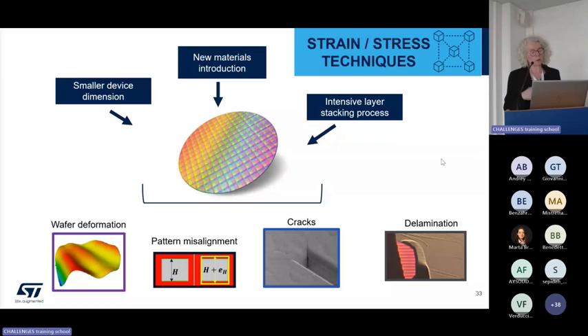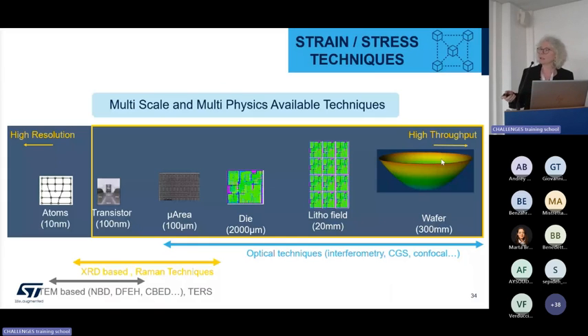So we've seen a growing focus on this demand for stress and strain measurement. What we have in hand in line is what is here in blue. We rely so far a lot on optical techniques. At the wafer level, we measure the deformation we call bow or warp. We can also use interferometry to get information at the litho level, the die level. But for a smaller area, not really the transistor but something like 100 micron square, we have to move at least to Raman or XRD. If we go even further, to the transistor itself, then we need to move to characterization techniques like TEM lamella, which is a very nice technique as well. So we still have a role to play here.